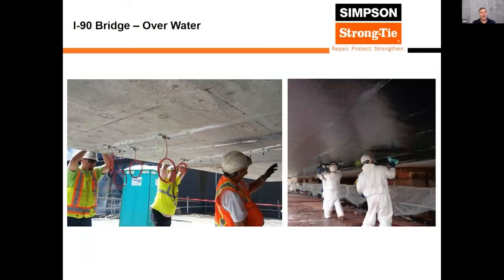Stepping back from surface preparations, concrete or masonry can have a lot of issues even past just getting the surface flat. There could be spalls, there could be cracks. All of those types of structural deficiencies typically need to be addressed before FRP is applied. On the left here, we have a team of workers doing crack injection. With FRP, pretty much any crack over 0.01 inch is going to need to be injected in most cases.